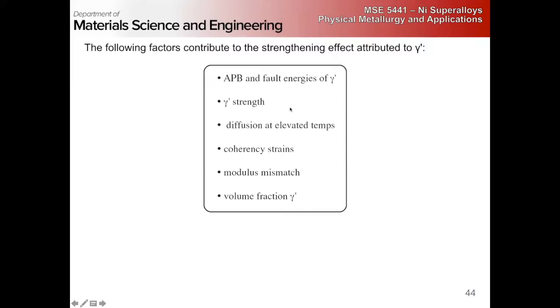Certain alloying elements might reduce these fault energies, others might increase them. The gamma prime strength is also a function of the composition. The diffusion at elevated temperatures, do I have heavy refractories in there or not? The coherency strains are going to be a direct function of the composition. The modulus mismatch and the phase fractions are all explicit functions of the composition.